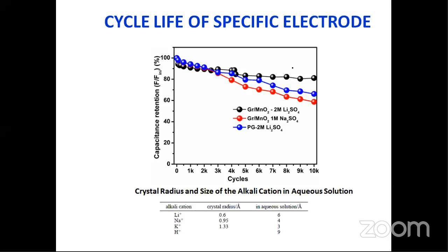Say for example, the cycle life of that system, the electrode materials, depends on the counter ions which we use. It depends on the electrolyte medium. Say for example, if it is a composite electrode, even up to 10,000 cycles. Look here, with respect to the counter ions, there is a huge variation in the capacitance retention. See here, almost 20% of capacity retention will vary with the counter ions. So the choice of electrolyte is a very, very important factor. Which electrolyte can give the better cycle life for our material? It depends on the electrode material. For that particular electrolyte, the cycle life is more specific, electrolyte specific.